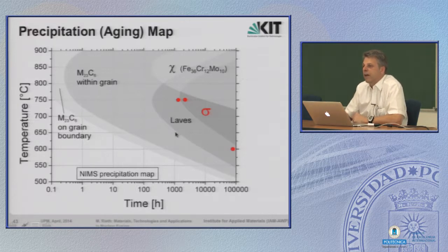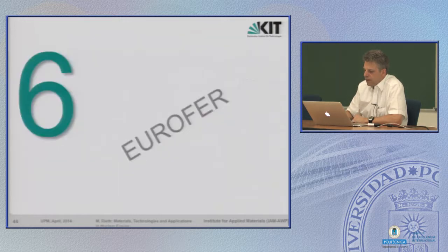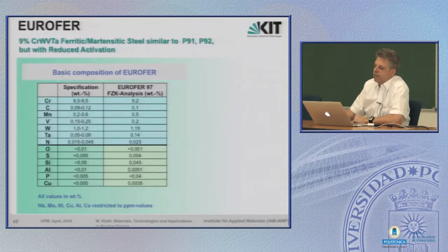And this is the main drawback, beside all the irradiation issues we have already treated, for 316 steels. Now let's come finally to the Eurofer steel. As you have already seen, it is a very easy mixture of a steel. There are only a few elements. That's chromium in the range of 9%, very low carbon content, 0.1% around.